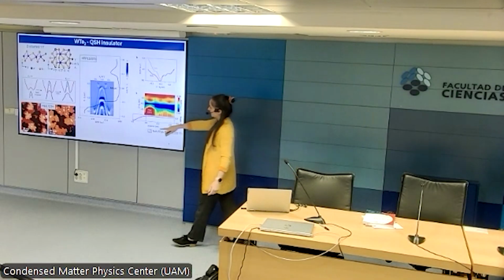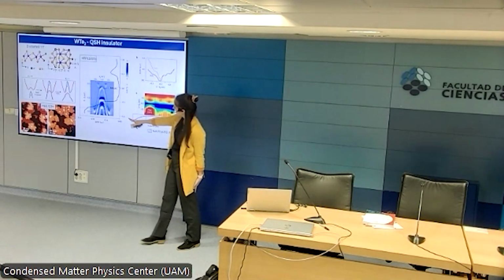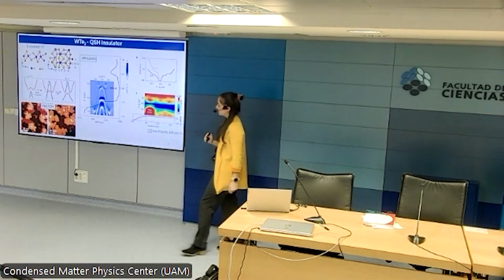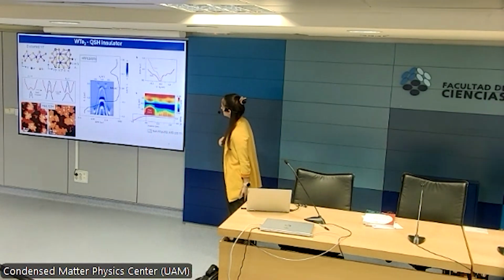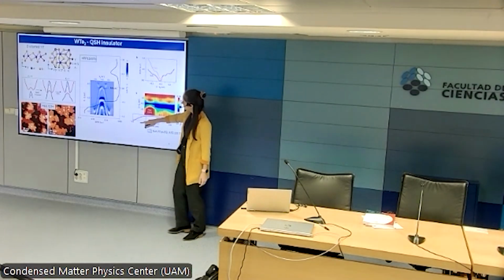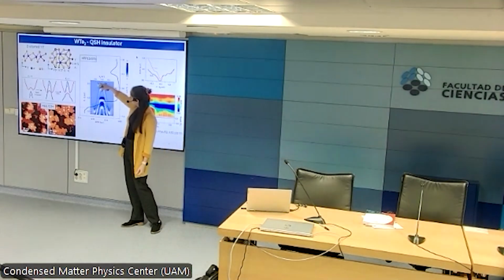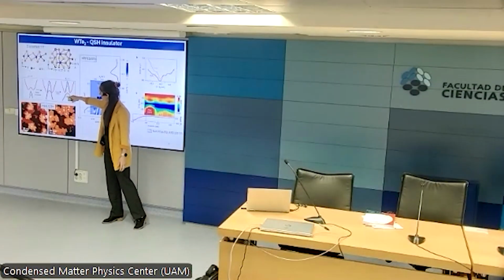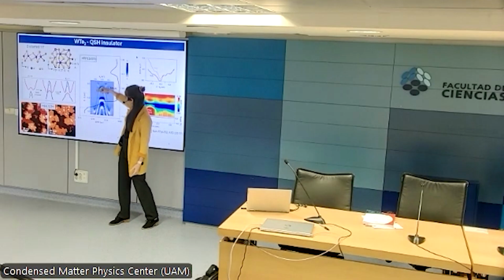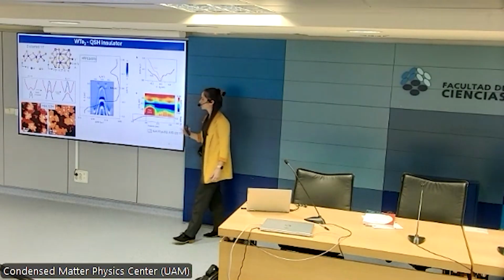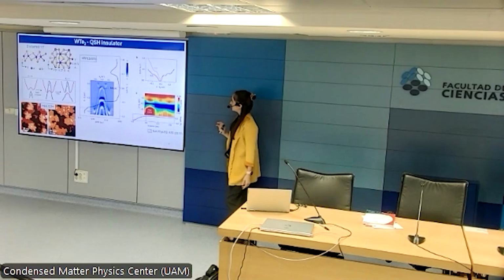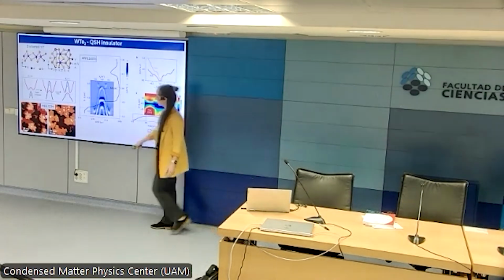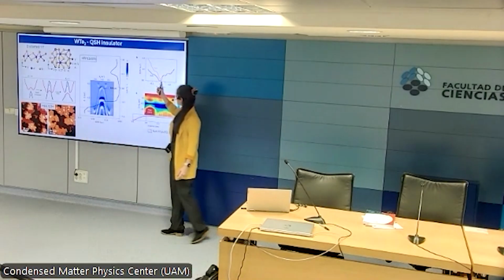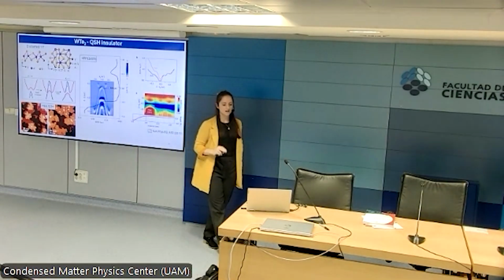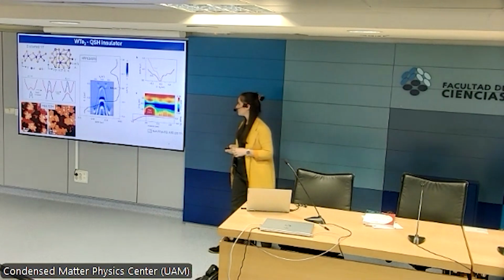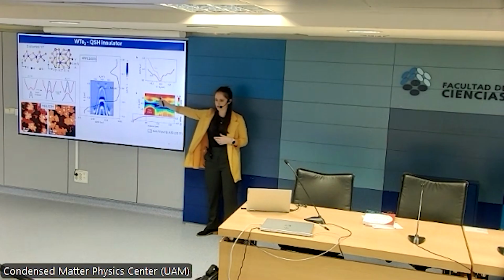You can see here that they grew tungsten ditelluride via molecular beam epitaxy, and they looked at it with STM. So they had these nice islands. The bright islands there are the TMD layers, and the dark areas are the graphite substrate, which they used. So they grew the material, they looked at it with ARPES. This is electron doped, so that these two pockets, this is the band structure that is predicted. The Fermi level should sit here. They doped with potassium, so the whole thing shifted down below Fermi, so they could see the entire band structure, which matched what was predicted. And then they demonstrated that it's topological by looking at the density of states going from the edge of an island towards the bulk. At the edge of the island, you can see that there's a V-shaped metallic density of states, whereas in the 2D bulk, there is a solid hard band gap of about 60 meV, and this is the signature of a topological insulator.